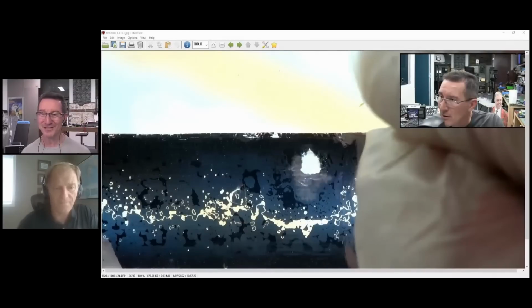Tell us your opinion. What am I seeing here? What do you think this problem is? Because you don't think that it is being destroyed by impulses on the mains. That's right. I think we should start going back and looking at the parts. Mainly these parts are non-hermetic. They're using a low-cost epoxy, so they're very cost-effective, easy to use, easy to choose. So it's probable that moisture got in during the application, and then that moisture was trapped by the non-hermetic case. There's also another scenario: there could be poor drying in the manufacturing process, and possibly water was put in there. That's very unlikely. So I think we've got a couple of easy explanations.